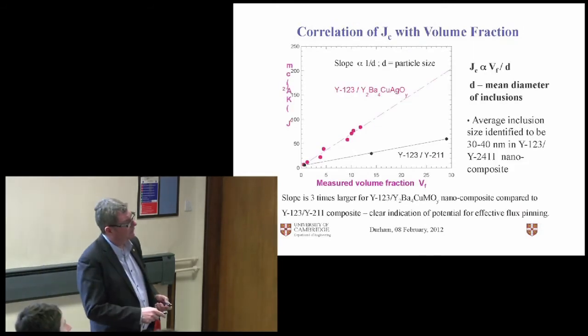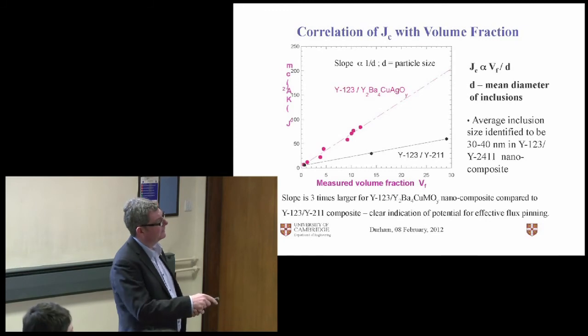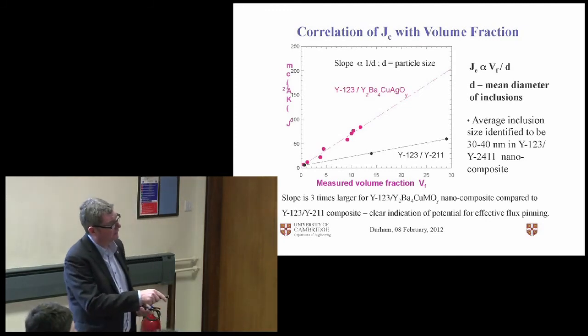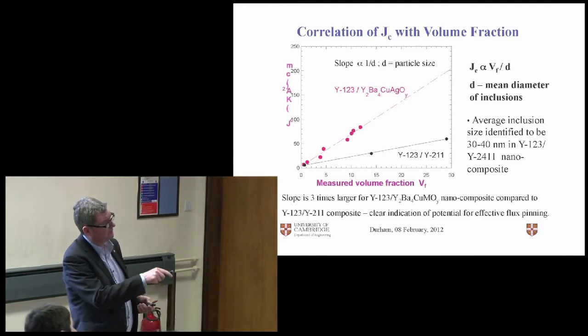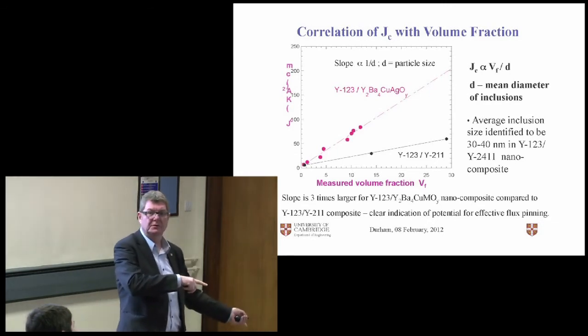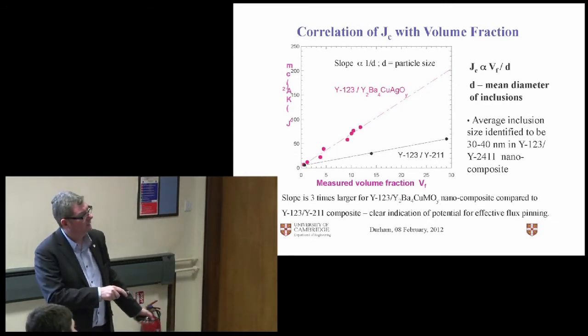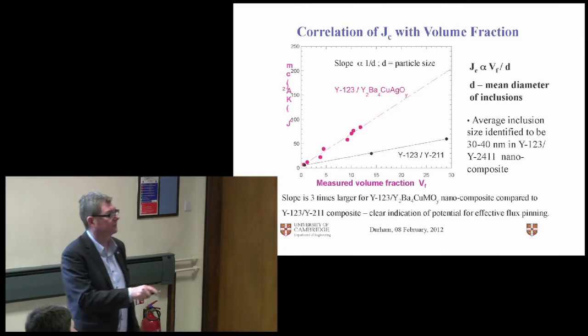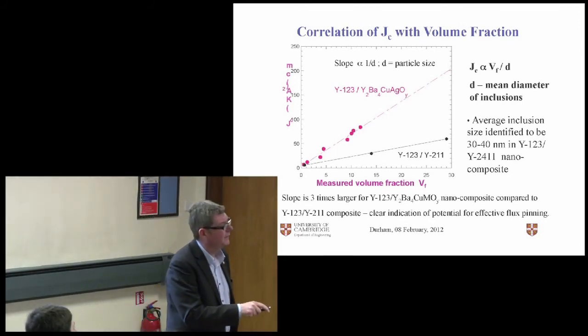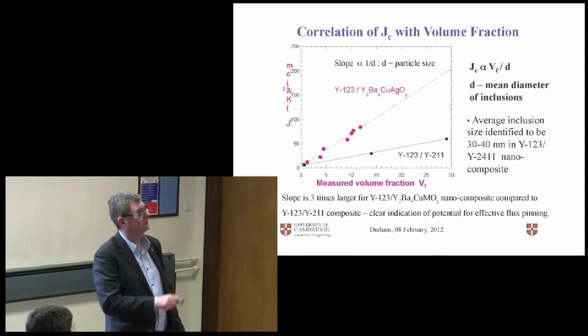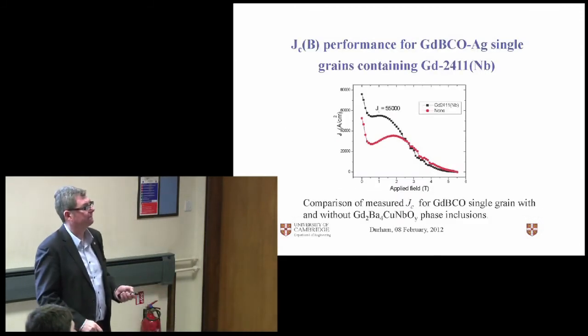And if we now look at JC, sorry about the axis, something went wrong here. If we look at volume fractions as a function of JC, which is comparable to the earlier plot for 211 I showed you, we get a fairly steep slope for the 2411 addition, whereas for 211 it's a much more shallow slope. So that tells you the principles of return give you a lot better JC properties if you use your 2,4,1 phase.